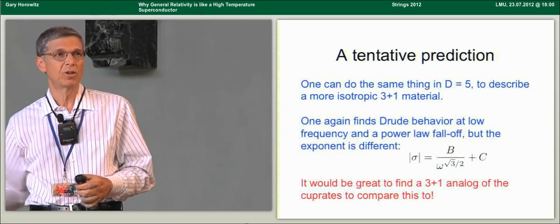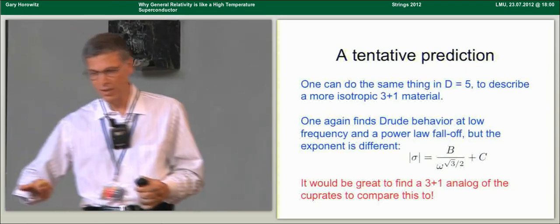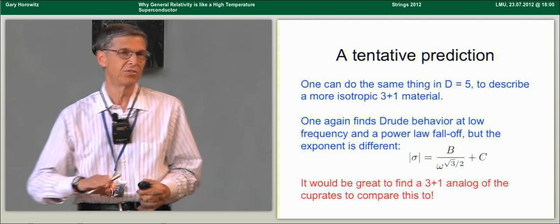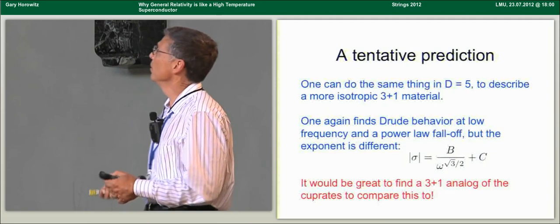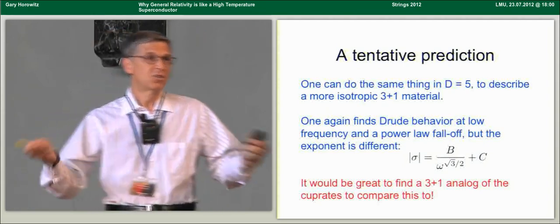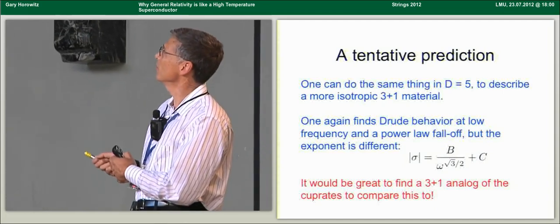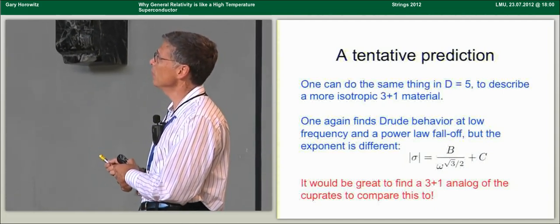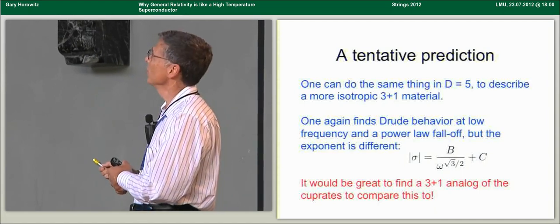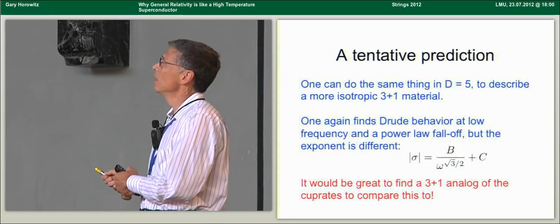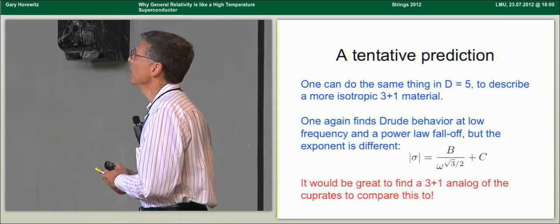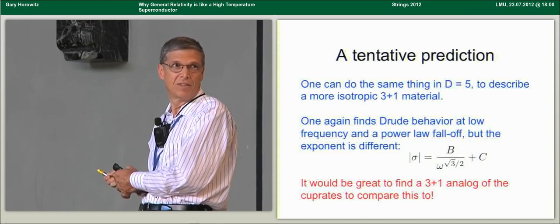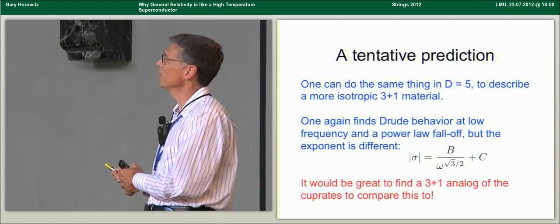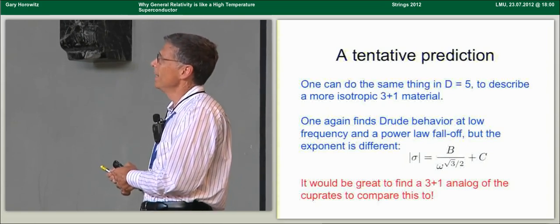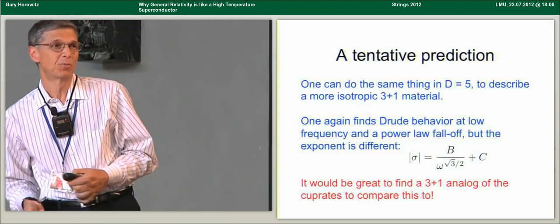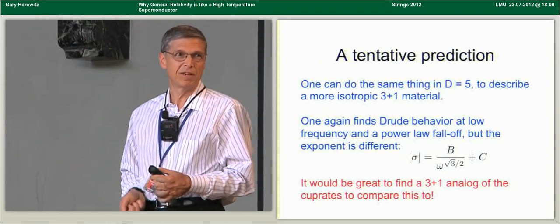This is appropriate for a 2+1 dual theory, which is the right arena for describing the cuprates because the conductivity is associated with these copper-oxygen planes. But we can ask, what happens if you had a more isotropic, strongly interacting condensed matter system? We redo the calculation in 5 dimensions. We find qualitatively the same result, a Drude behavior at low frequency, then a transition to a power law fall-off regime, except now the exponent is different. So the exponent does depend on dimension, and we find that it falls off like 1 over omega to the root 3 over 2. And it would be great to find a 3+1 analog of the cuprates to compare this to. So far, I haven't been able to find one.